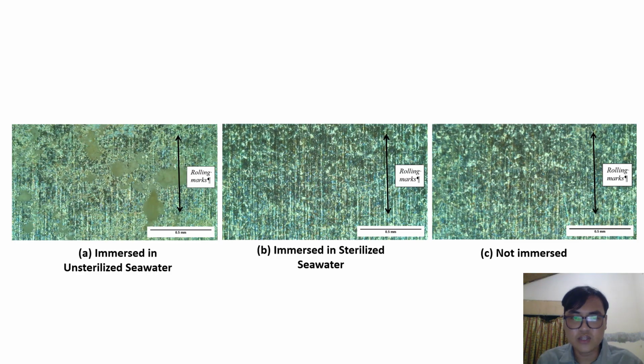Now let's visualize these results through morphology. In the unsterilized seawater, the surface showed a patchy attack. We observe irregular deposits identified as iron sulfides, resulting from the activity of sulfate-reducing bacteria. However, as the biofilm matured, it became thick and acted as a barrier, inhibiting oxygen and slowing down corrosion in later stages. In the sterilized seawater, the surface remained relatively clean, with original rolling marks still visible.